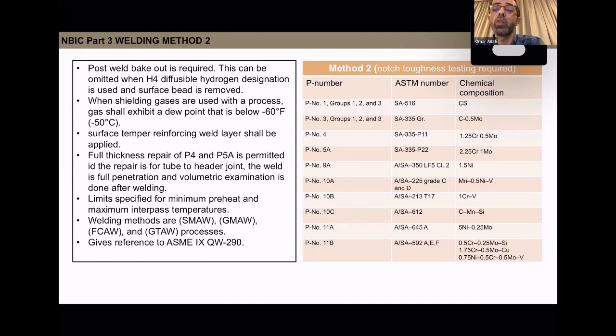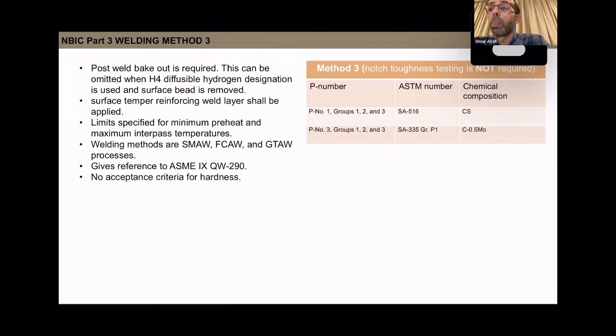The welding methods are SMAW, GMAW, FCAW, GTAW, and they give reference to QW-290. This is the welding method for P-number 1 and P-number 3 when impact toughness is not required. So this is mainly for hardness. Post-weld bakeout is required. In this case, it can be omitted when H4 diffusible hydrogen designation is used and the surface bead is removed. So in order to waive this post-weld bakeout, we need to use H4 diffusible hydrogen designation, and the surface bead needs to be removed.